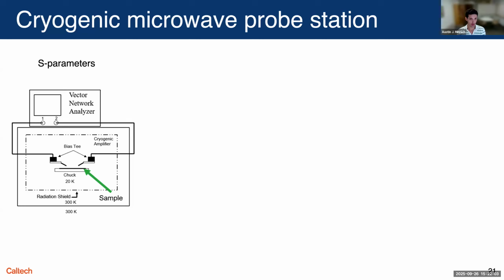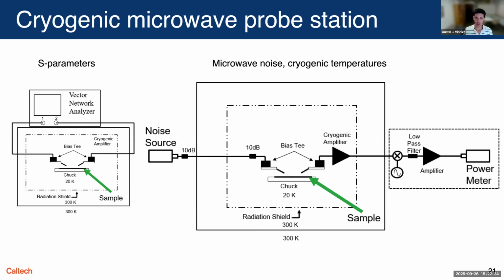And to do that, we're going to do S parameter and cryogenic noise measurements. So the S parameter measurements are pretty straightforward. So we have a cryogenic probe station, which I'll show a picture of in one slide. And we can maintain the sample down to 20 Kelvin, and we use a VNA to send in the signals. The microwave noise temperature is a bit trickier, but it's something we routinely do. And the key idea is you send in different levels of microwave power, and then you look at the amount of power coming out, and through a quantity called the Y factor, which is the ratio of those noise powers, you can get the noise temperature.